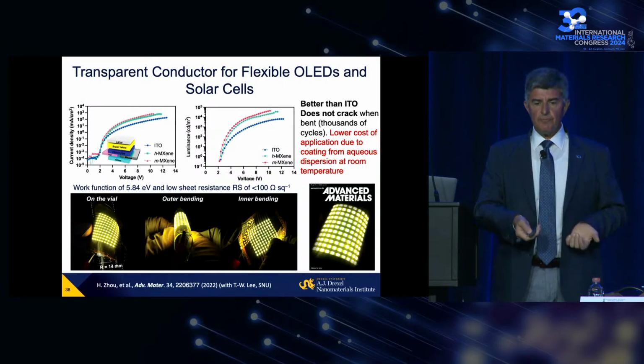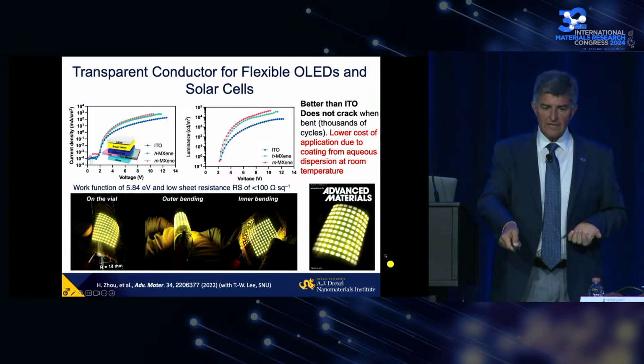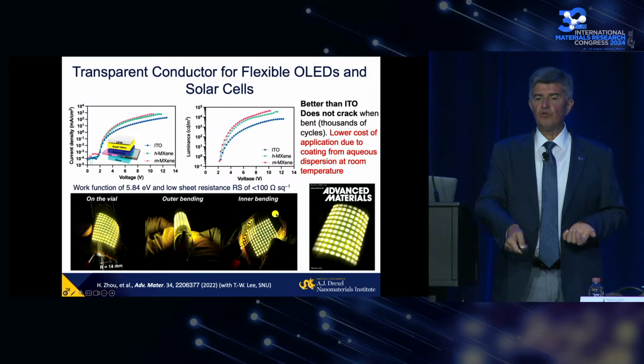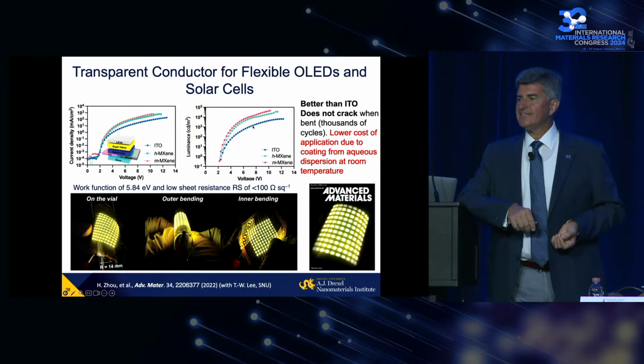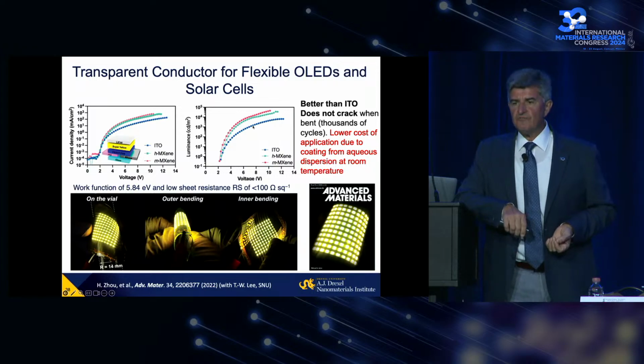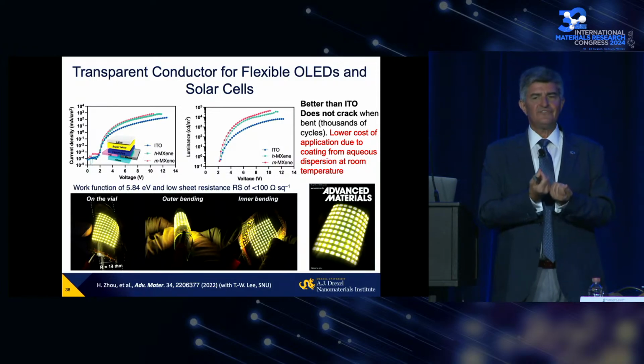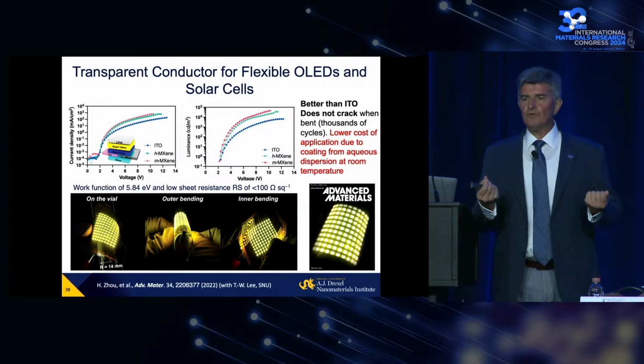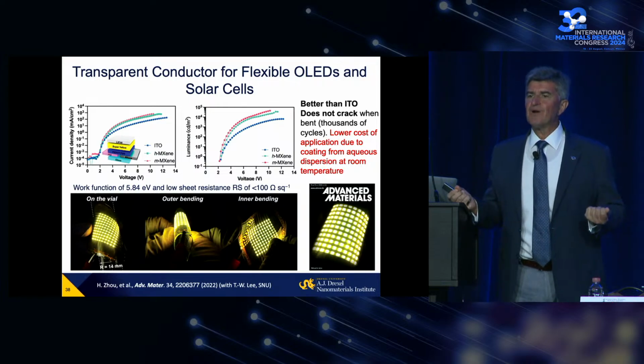ITO cracks when you bend it, so their goal was to make devices which are flexible, bendable, foldable. But because we can tune the work function in MXene, on this logarithmic scale, luminance and brightness also increase by an order of magnitude. So they not only make it flexible, they make it also 10 times brighter.